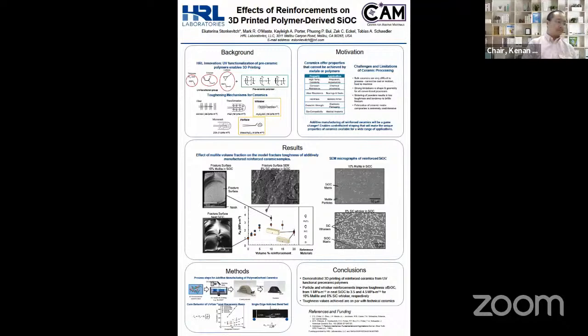As you can see from the K1C versus volume percent reinforcements plot, our neat, unreinforced 3D printed silicon oxycarbide material is right around 1 MPa root meter. With the addition of mullite particles, we can see that the toughness increases to 3.5 MPa root meter at 10 volume percent particle loading. With the addition of 8 volume percent silicon carbide whiskers, the fracture toughness increases to 4.5 MPa root meter. These values are close to toughness values seen in technical ceramics such as silicon carbide and alumina.